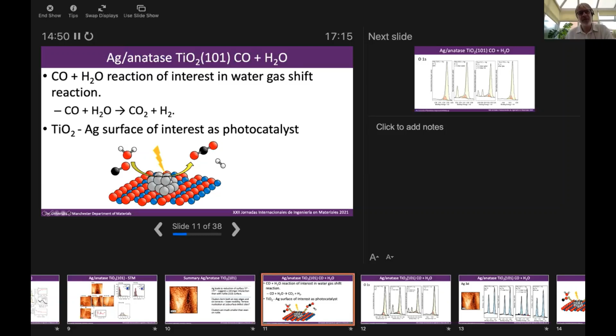And we know generally in the water gas shift reaction, lower temperatures improve the yield of carbon dioxide, and the catalysts used are mixtures of base metals and so on. So we thought we'd look at this titanium dioxide silver surface, because it is of interest as a photocatalyst, and also it's a model for what's happening in car catalysts, where you take carbon monoxide and convert it to CO2. But obviously there the substrates tend to be things like ceria or yttria, which have a much higher oxygen mobility, and they're thought to take part in the reaction. We hope this might give us some idea about the mechanisms involved. Is it due to adsorption on the oxide, which leads to the presence of the silver, which then causes the conversion to CO2, or is there something happening on the silver?